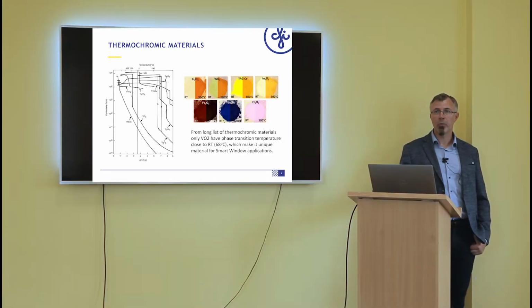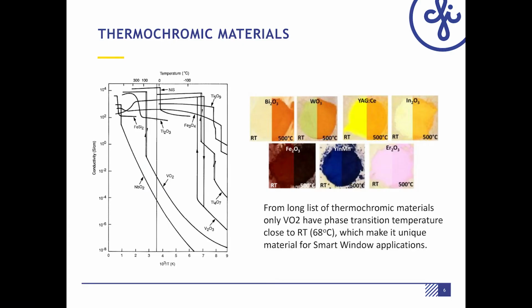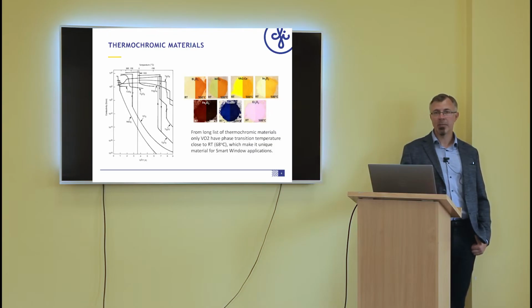There are a lot of other inorganic thermochromic materials. You can see a lot of them on this slide. But unfortunately, only one, vanadium dioxide, has a phase transition which is relatively close to room temperature, that is 68 degrees Celsius, and for real application it is necessary to shift it closer to room temperature, and in the next slides I will mention methods which we can use to achieve that.